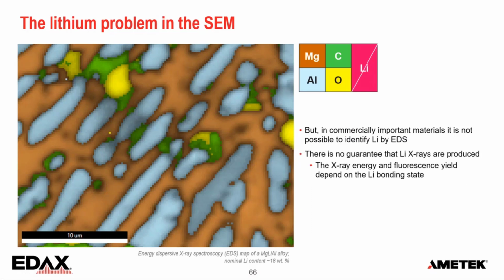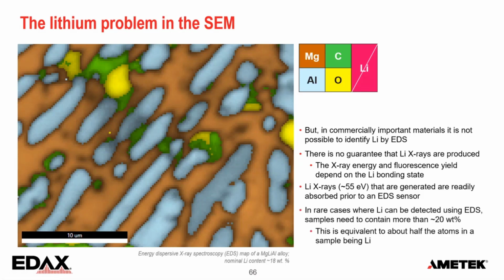Now, one additional problem with lithium detection is that you have no guarantee that there are going to be any X-rays, even if you have lithium, because it depends on the bonding type of lithium, if there is actually an electron available to generate an X-ray. That's not always the case. And obviously, the very low energy of lithium X-rays makes that they are very easily absorbed before they ever reach the EDS sensor. Now, there are cases where you can see lithium with EDS, but you need to have more than about 20 weight percent lithium to even see it. Otherwise, any lithium signal is going to be absorbed. So if you have about half the atoms in a sample being lithium, then you can see it. Otherwise, it just doesn't give you any signal.